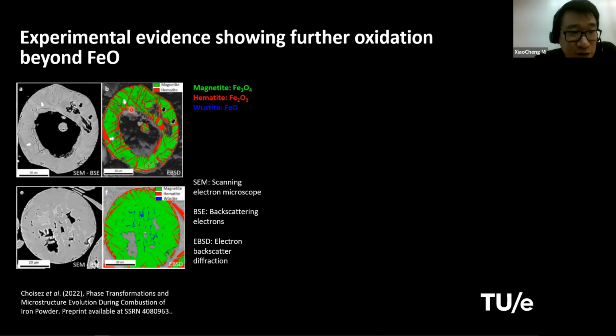So these are some particles burned from one of our burners, and these were given to some collaborators. She was at the Max Planck Institute for Iron Research in Germany, and they managed to cut the particle and look at the cross section of these particles, using backscattered electrons to look at the different crystalline structures of different parts of the particle. And this allows us to know where the particle is magnetite, like Fe3O4, where is hematite, and where is other things like wüstite or iron itself.